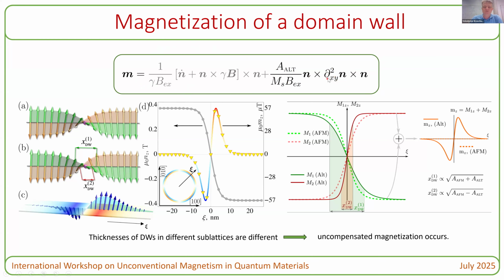It is already clear that due to this differential operator, we should expect some non-zero magnetization for a non-uniform solution for M. If the domain wall is oriented exactly along the nodal planes, nodal directions, which here coincide with the X and Y directions, then no magnetization is expected. But if it is oriented, let's say, at 45 degrees, these terms will give the maximal effect.